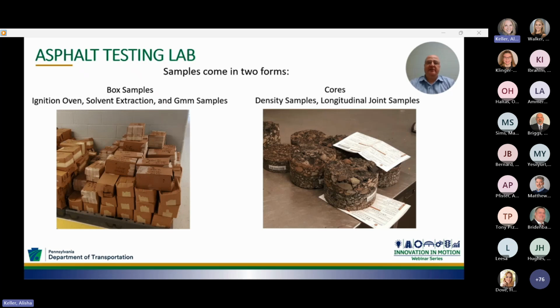Box samples are used in ignition oven, solvent extraction, and GMM verification tests. When we perform ignition oven or solvent extraction tests, we determine the asphalt content of that mixture and then grade the remaining aggregate to determine the amount of material passing the primary control sieve and the number 200 sieve, as these are used in contract payments. GMM testing, also known as AASHTO T209, determines the specific gravity of asphalt mixtures, where we verify the specific gravity value submitted by the contractors. Core samples are used in density testing, which determines the amount of compaction that the contractors achieve. Here, note that cores are also used for testing the longitudinal joint samples.